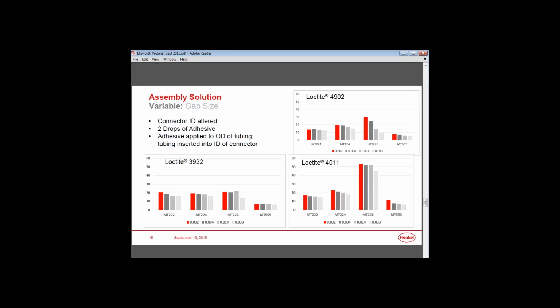So next we're going to look at gap. In this case we altered the connector that we listed that we were using. So we altered the ID of that connector. We still maintained 2 drops of adhesive for this testing, and again, the adhesive applied to the OD of the tubing. So you'll also see in this case that there isn't a huge effect with the variation in gap. I will note that once we got to the largest gap listed, 0.033 inches, in that case you'll see in some of the data it's starting to drop off. We did do some experiments in this case with 3 drops of adhesive, and then we were back to the standard or starting strength that we had with the smaller gap size.